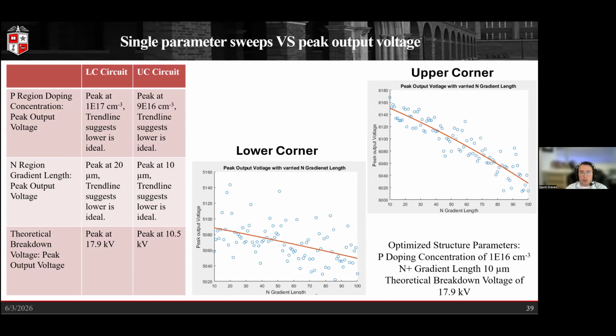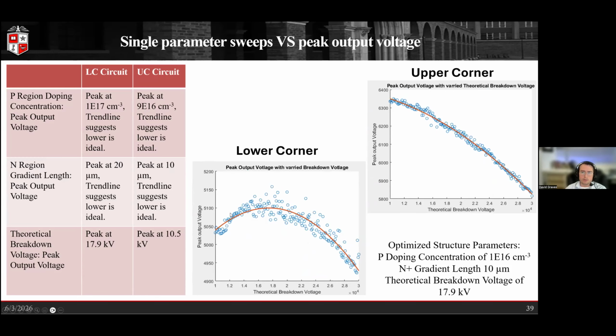We found some small correlation with the N-region gradient length. We found a peak at 20 microns. However, the trend line suggests that an abrupt junction is lower. And then the same for the upper corner. We found some small correlation. We can see we're only getting a difference of 100 volts, which is relatively small when we're looking at the overall percentage increase. And then looking at the theoretical breakdown limits, we find a peak for our lower corner circuit at 17.9 kV. And with our upper corner, we end up with a peak at 10.5 kV.